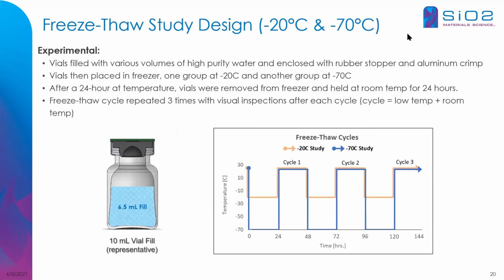So one of the studies we did was a freeze-thaw study at minus 20 and at minus 70 degrees C. And the idea here was really to assess robustness of the container compared to glass. We took a group of 10 ml vials filled with 6.5 milliliters of liquid, and then cycled them to minus 20 and minus 70 respectively, held them for 24 hours, then room temperature for 24 hours, and repeated that cycle 3 times for both the minus 20 case and the minus 70 C case.